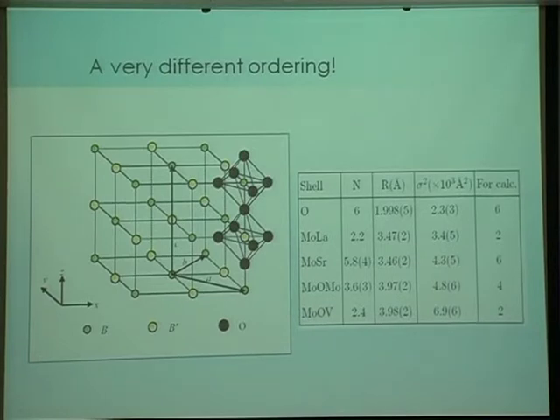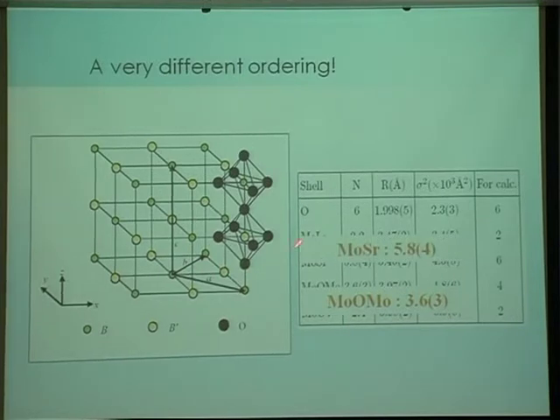But if we have completely disordered, that means each of these sites has a possibility, each site will be 50% occupied by vanadium, 50% by molybdenum. If it happens that way, then statistically every molybdenum will find 3 vanadium and 3 molybdenum. So the possibilities span 0 molybdenum to 3 molybdenum. Experiment tells you every molybdenum finds 3.6 molybdenum, more than that. Even bigger problem, I have La and Sr, and there are 8 small cubes, so 4 La and 4 Sr is expected around it, and molybdenum finds 5.8 Sr. For some reason, molybdenum finds more molybdenum and more strontium around it, some kind of a microscopic phase separation.